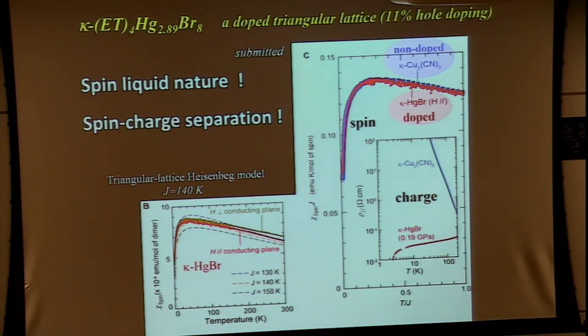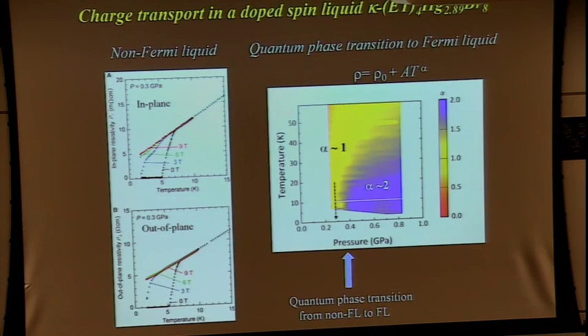It's very striking. Okay, this is the scaled susceptibility as a function of temperature, J multiplied by the spin susceptibility. And blue symbols are the susceptibility data of the spin liquid insulator. And red symbols are the 11% hole doped spin liquid. Nearly the same. So this means the two materials show exactly the same behavior in the spin sector. However, let's take a look at the inset, the resistivities. The spin liquid material is insulating, a good insulator. However, the doped spin liquid shows a good metal. And in reality, this metallic behavior is non-Fermi-liquid-like, T-linear.